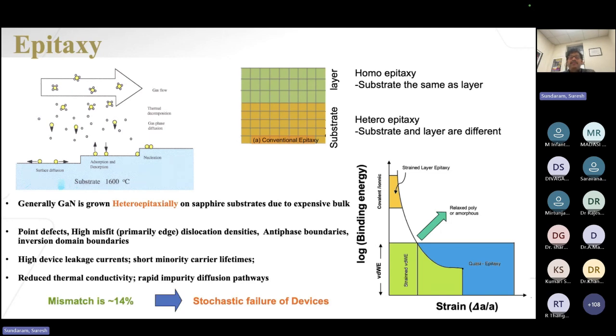So the lifetime of your devices, even though we have reliably performing materials, it leads to stochastic failures. We want to reduce the dislocation density, but we have almost 100,000 hours of working devices, even though the dislocation density is high in these kinds of materials. We have reliable performance, but we want to eliminate these dislocations.